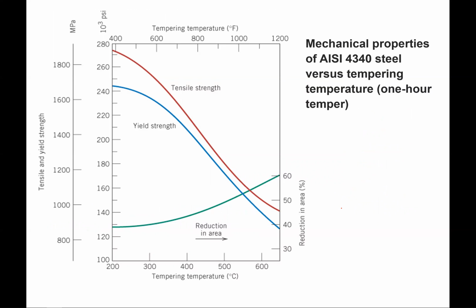So we could go ahead for a particular steel, and we could plot out the tensile or yield strengths versus the tempering temperature. And in this particular case, these were all done for a 1 hour temper. And so we can see that at the lowest values of tempering temperature, like 200 degrees C, we have some very high tensile and yield strengths and reasonable ductilities. That's not a bad ductility at 40% reduction in area. It's not bad at all.